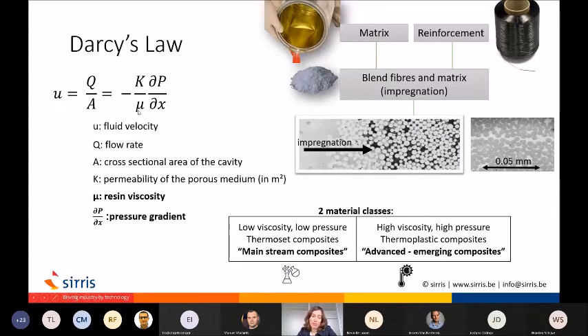And then the other one, which is also a very important parameter, is the viscosity of your resin. You can imagine that if the resin is more fluid-like, it's easy to impregnate. If it's more viscous, more like honey, it's much more difficult to impregnate. And that leads to two material classes that we can use to divide composite manufacturing technologies. On the one hand, we keep these two parameters low for a good speed of processing.